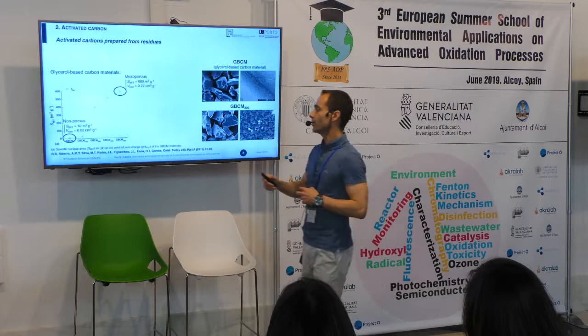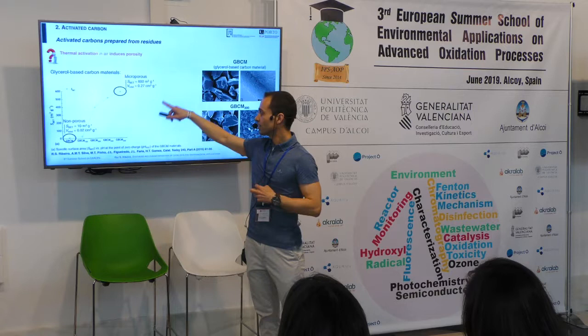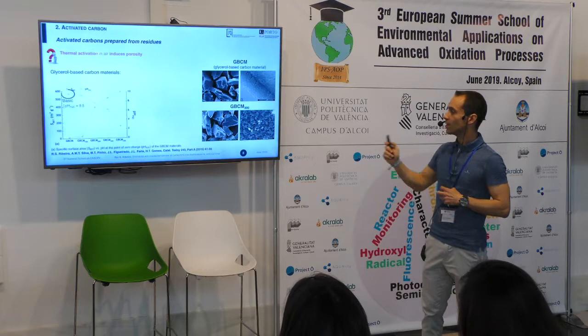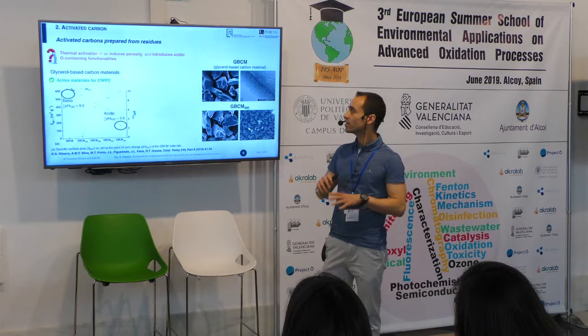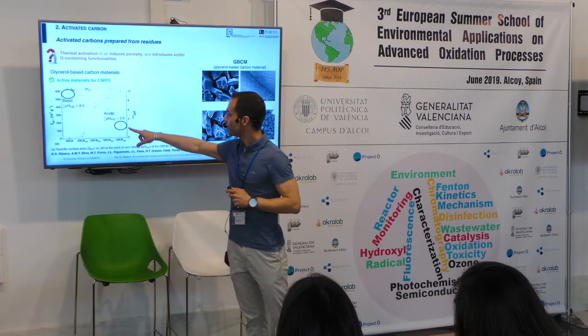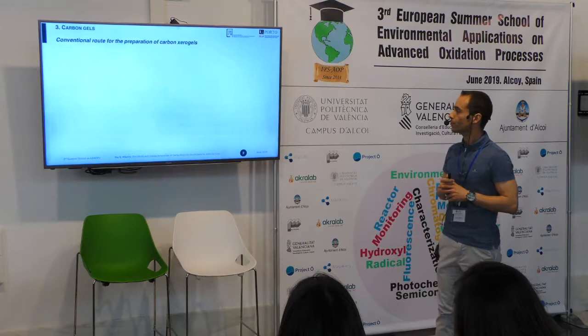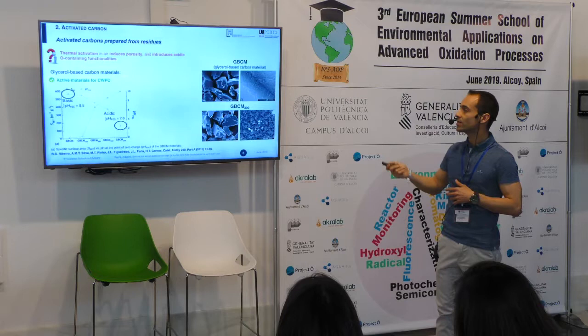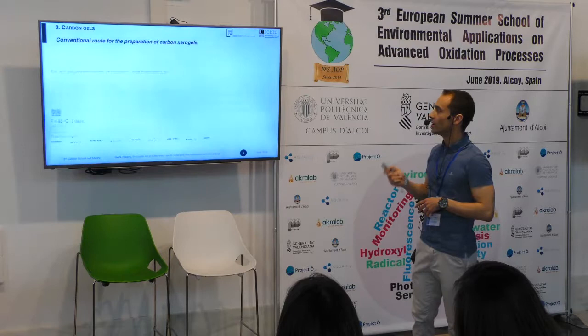As we can see, the specific surface area of the materials increases as the activation temperature increases. While at the same time, the amount of oxygen-containing functionalities at the surface of the carbon material also increases, as suggested by the decrease of the pH at the point of zero charge. These materials were also active for catalytic wet peroxide oxidation.